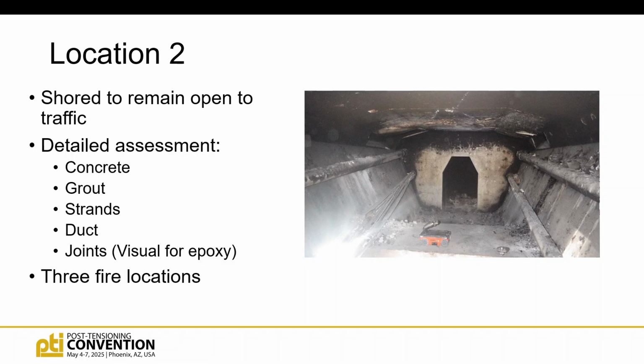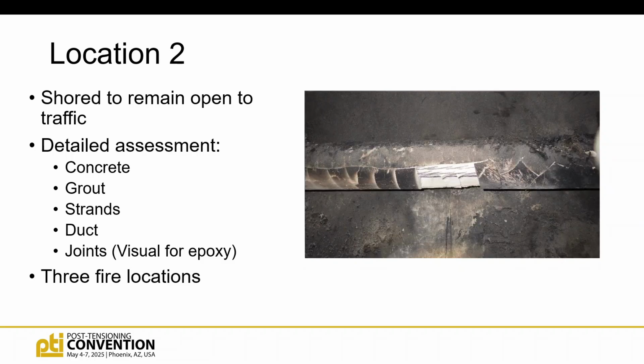But that was fire number 1. Here's a section of the grout on the tendon we were concerned about. No, actually, this is one of the good tendons, and that grout had been removed. So you can see the cracking in the grout. There is no duct on that tendon. It's been melted off or burned off. I'll show you what that looks like later. And that was where we had chipped out the grout to expose the strands, and they were in actually pristine condition. They had been undamaged, and I'll walk through our grout testing protocol here in a bit as well.